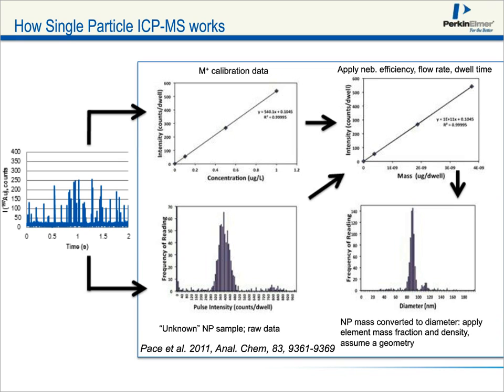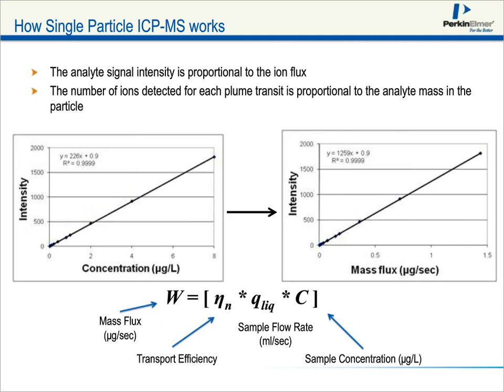And the formula to use for such is the following. You're going to have the mass flux, which is equal to the transport efficiency of the system or your instrument that you're using, the sample flow rate, how much liquid we're introducing, and the concentration. And that's going to give us the amount of mass by time. And we're going to use that to convert the intensity of the nanoparticles acquired over a short time, which is usually 300 to 500 microseconds. And we're going to be able to get the amount of mass generated from that nanoparticle.